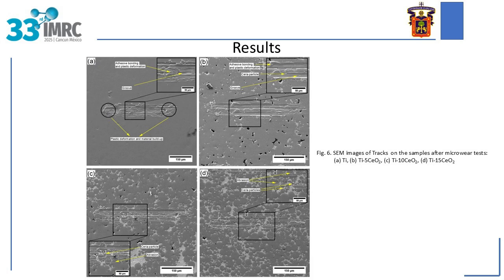Finally, the wear tracks were analyzed by SEM images. In the titanium image, the footprint with the largest dimensions was observed, measuring approximately 100 micrometers in height. The footprint exhibited several areas of adhesive bonds with plastic deformation, dragging and accumulation of materials towards the end of the footprint. Additionally, grooves were observed, likely resulting from detachment of material or abrasion caused by its dragging during contact.